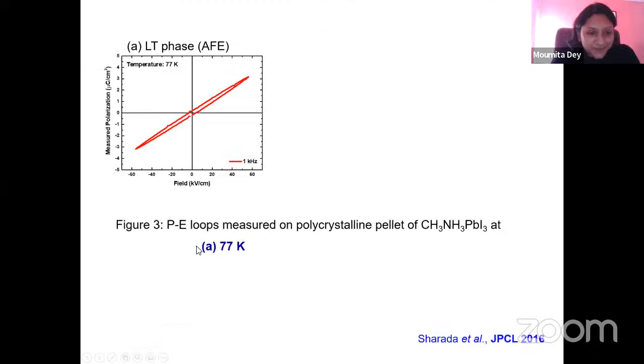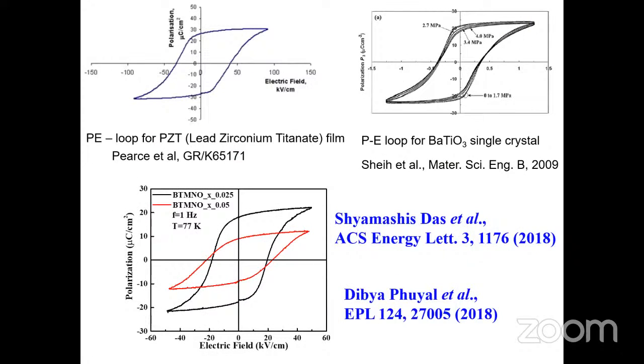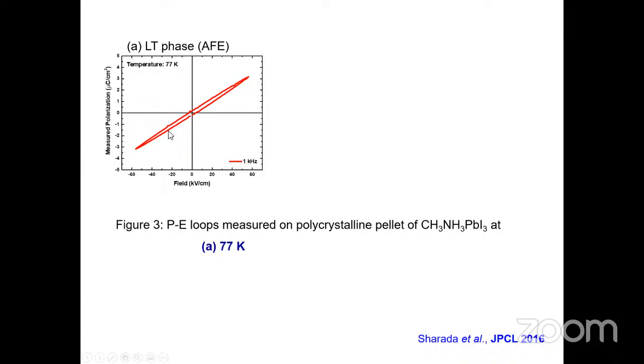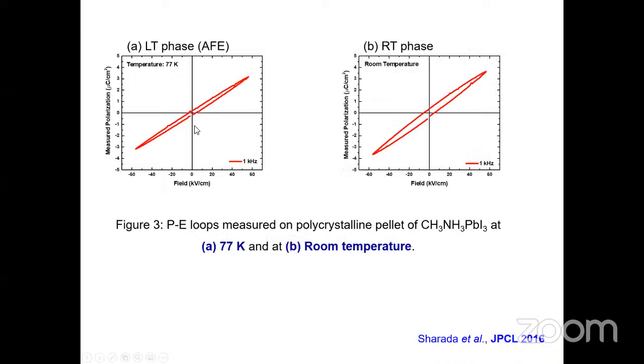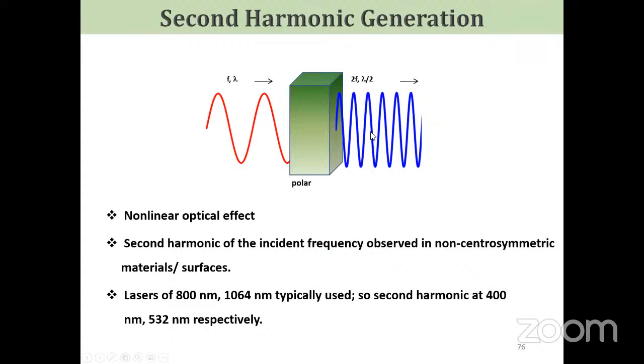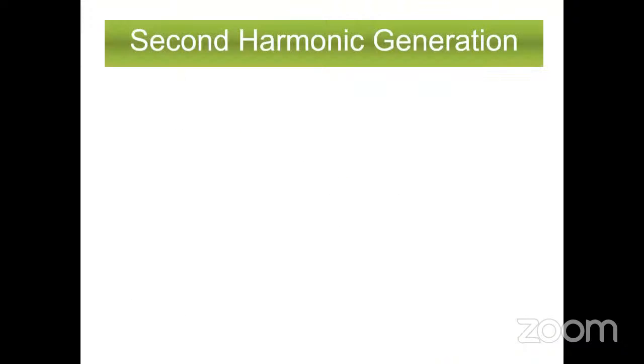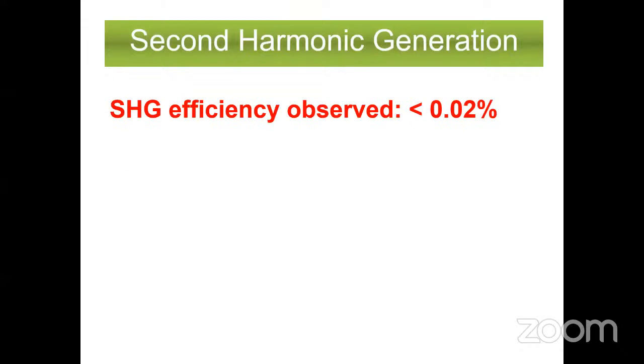No problem. So basically, the loop measurement we did, we found that at low temperature, I know this material to be antiferroelectrically aligned. So I don't expect a loop, and I see the polarization. It looks like this. And at room temperature also, it looks essentially like that, telling me that the dipoles are not ferroelectrically aligned. We'll look at it also in terms of second harmonic generation. Let me skip that part. Essentially, there's no second harmonic generation, which says that the structure is centrosymmetric, which cannot be ferroelectric.